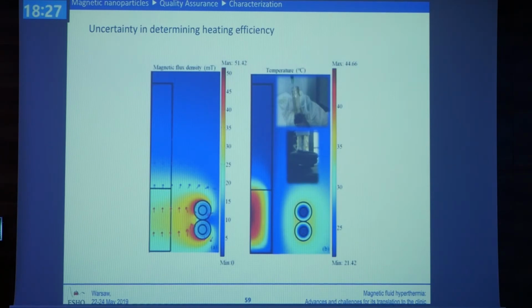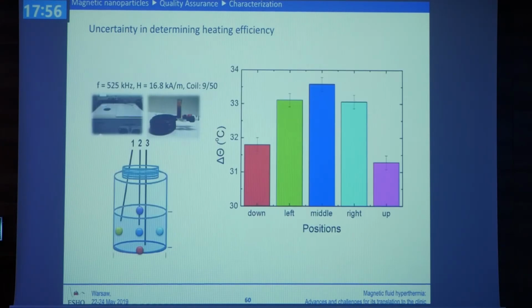Now, with what sort of accuracy or certainty do we measure the heating efficiency of nanoparticles? We can simulate. First of all, we see that inside any heating system where we want to measure the SLP of the nanoparticles, the magnetic field is not uniform. You don't have a uniform magnetic field, so you have to know where you're measuring and what your magnetic field is at this point, and that you can do only by simulations or by measuring the magnetic field when the coil is on. The other thing is, where do you measure?